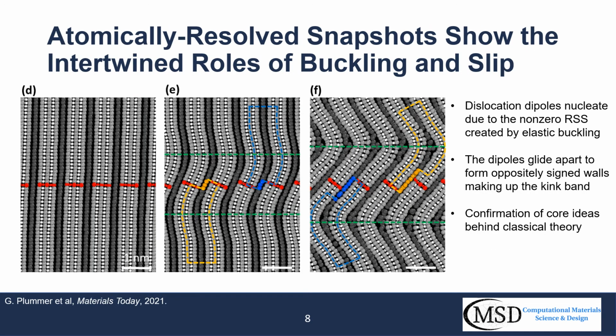The close connection between elastic layer buckling and kinking becomes completely clear when looking at atomically resolved snapshots of another simulation showing the nucleation and growth of a single kink band. Initially, the elastically buckled layers create a non-zero resolved shear stress on the basal planes. You can note the slight offset from the vertical in the leftmost image there. The resolved shear stress quickly becomes large enough to nucleate dislocation dipoles, which then glide apart forming the kink boundaries.